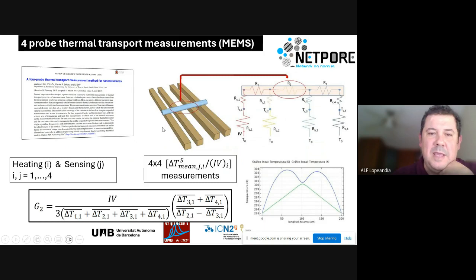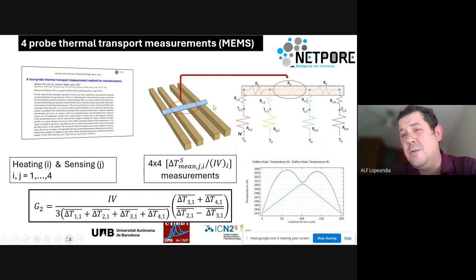Now, this is a COMSOL modeling of one line that has been heated with a nanowire in the middle. And the typical profile that we get in a line that is simply sensed is this triangular shape. That is, if we heat the line, we will be able to measure the temperature drop. These are lines number 1, number 2, number 3, number 4. If we heat one line, we will be able to measure the temperature in the 3 other lines. The resistive measurement will give us the average temperature, but we can extrapolate the temperature at the contact point easily because that equation can be solved analytically.